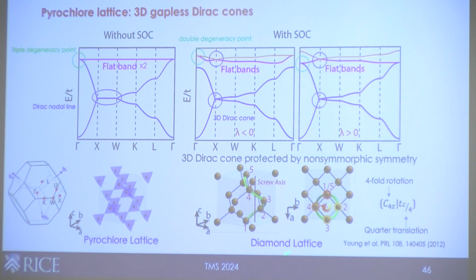So it's easier to see this non-symmorphic symmetry in the diamond lattice. If you follow this green screw, you will see that there is a 4-fold in-plane rotation together with a quarter translation along the c-axis. This gives you the screw axis, the screw operation. So this is the non-symmorphic symmetry. And theoretically, it's already known that in the diamond lattice this non-symmorphic symmetry will give you a gapless 3D Dirac point. This maps back to the pyrochlore lattice.